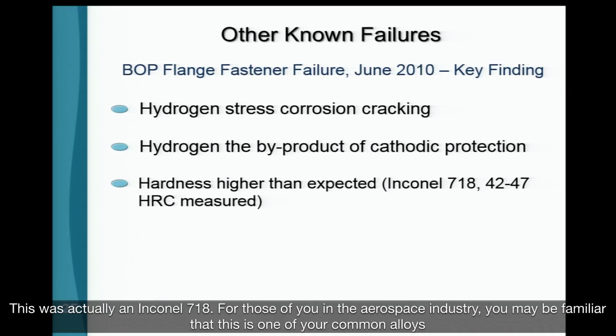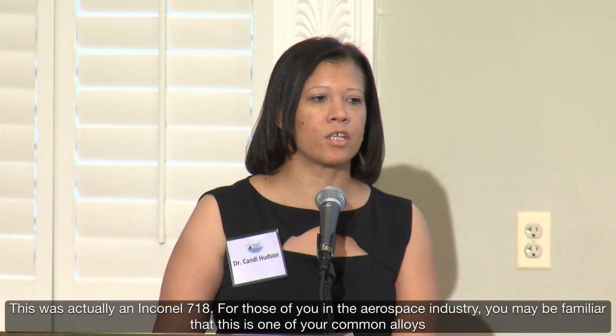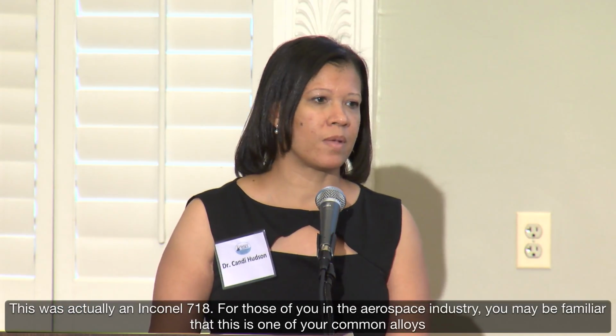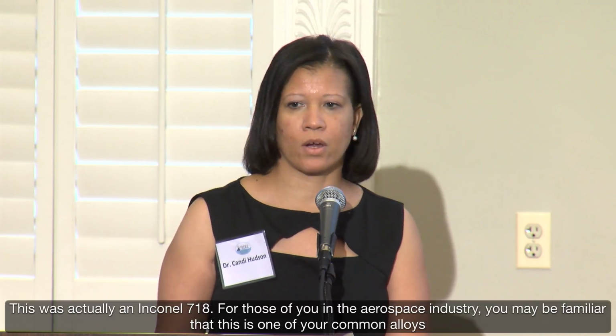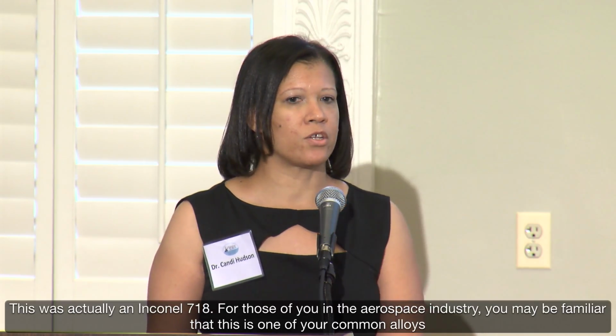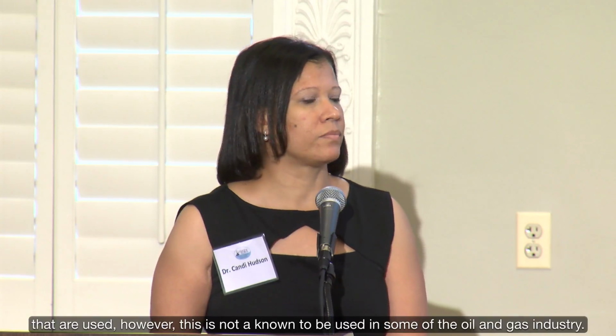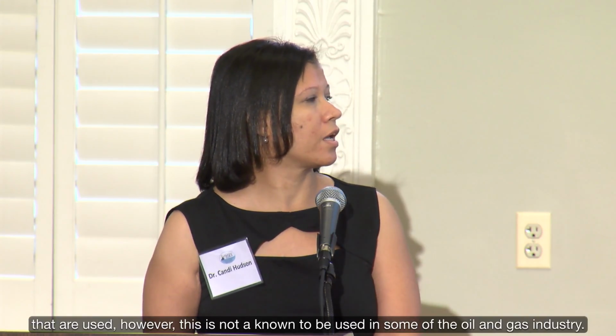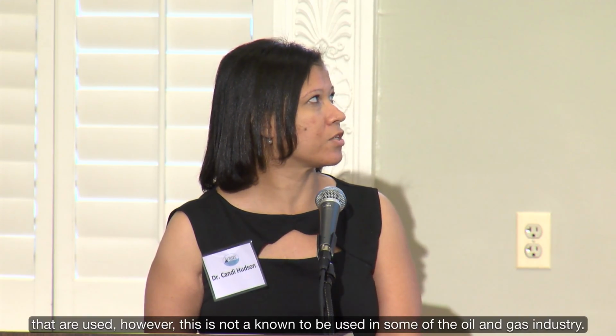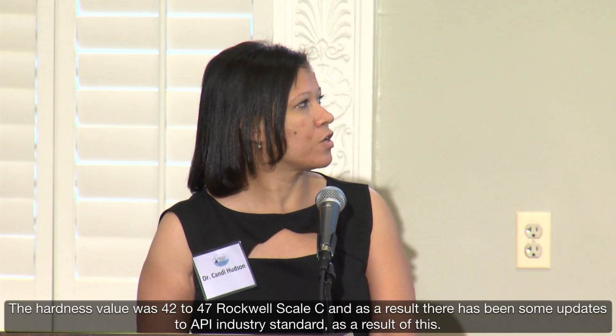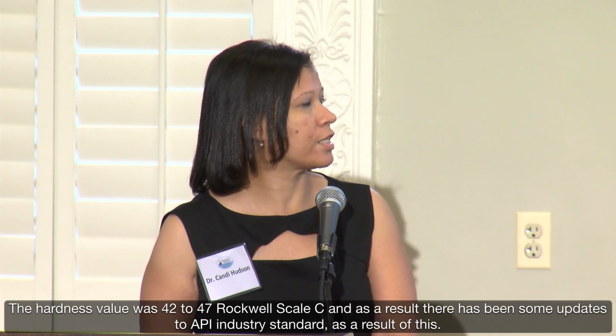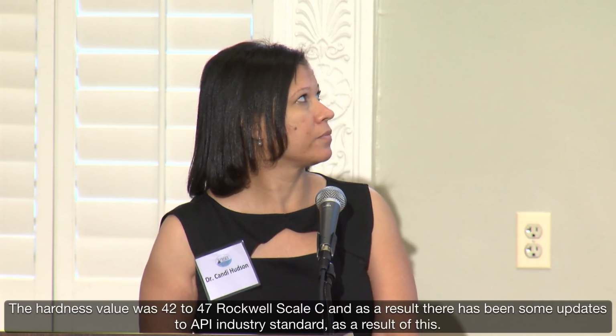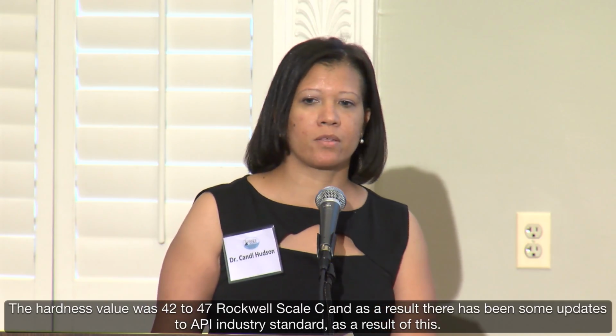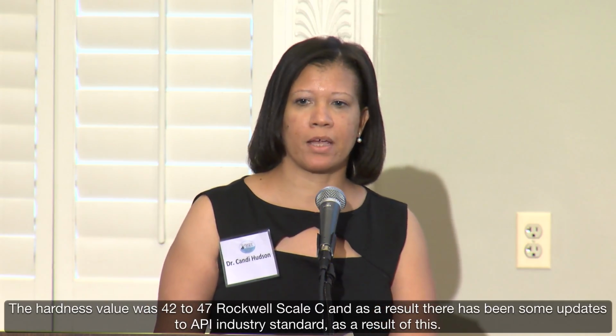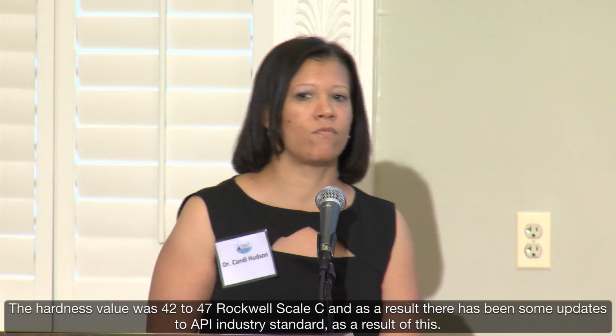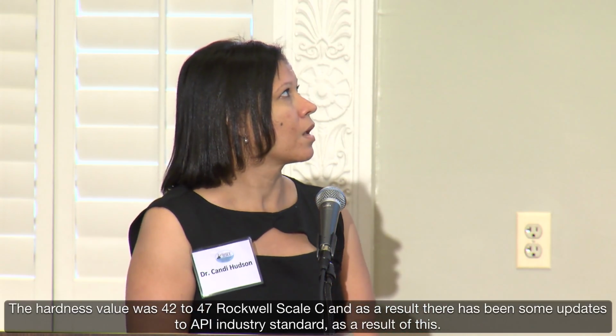This was actually an Inconel 718. For those of you in the aerospace industry, you may be familiar that this is one of your common alloys. However, it is not known to be used in some of the oil and gas industry. The hardness values were 42 to 47 Rockwell scale C, and as a result, there have been some updates to the API industry standard.